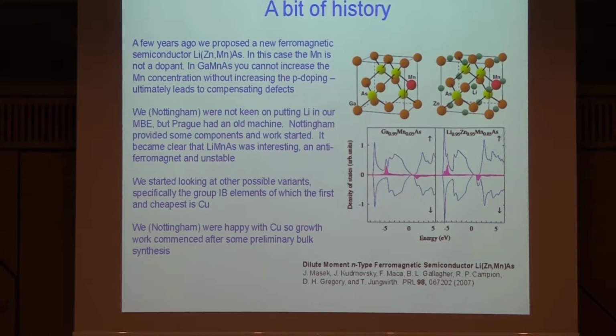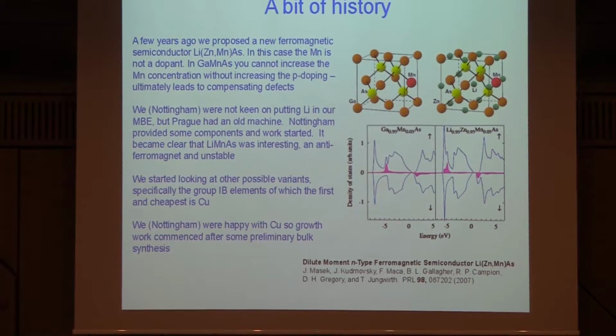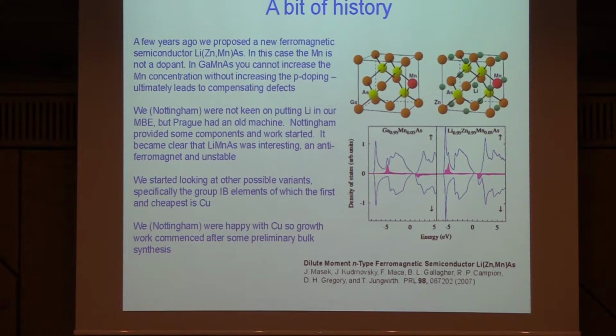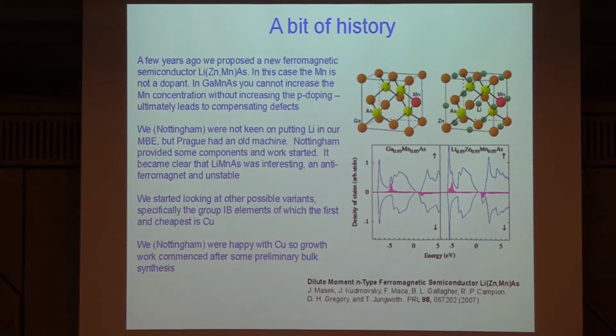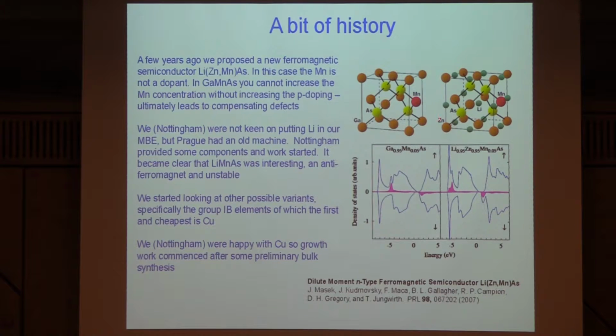We started many years ago growing gallium manganese arsenide, and it was a wonderful prototype material to look at magnetic phenomena. The trouble with gallium manganese arsenide was that the manganese is substitutional on the gallium side, but it's a dopant. And the trouble is, if you try to put lots and lots of manganese into gallium manganese arsenide, the doping is effectively frustrated, and you have solubility problems because it's a dopant, and also it ultimately leads to compensating defects as well. So you're always fighting this thermodynamics.